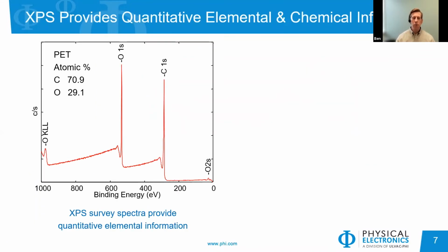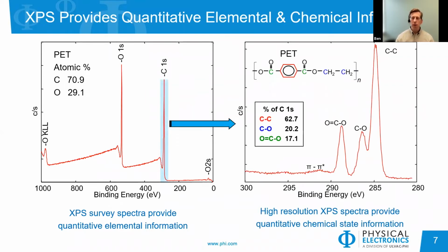And so a short example here, this is what a typical survey spectrum looks like for XPS. You see that you have strong peaks that would be representative fingerprints for different elements at specific binding energies. You'll notice also that some elements will have multiple peaks, and so you can use those again for fingerprinting. And one of the real advantages of XPS is the ability to not only get elemental information, but to get chemical state information, short order chemical state bonding information.